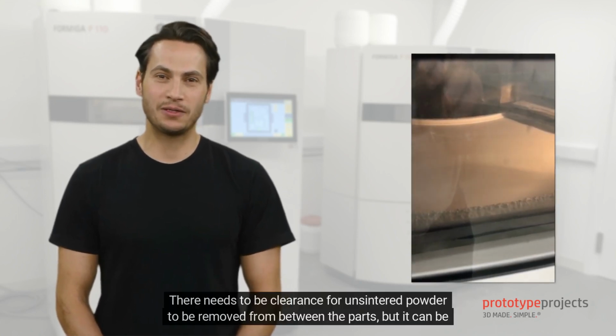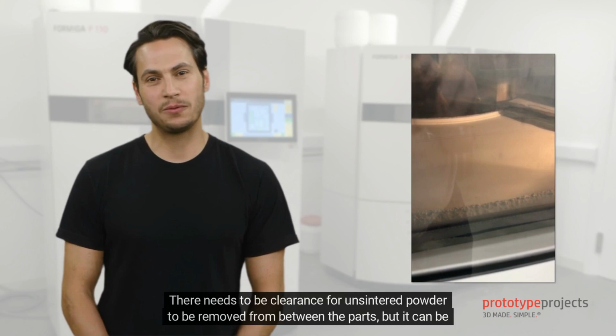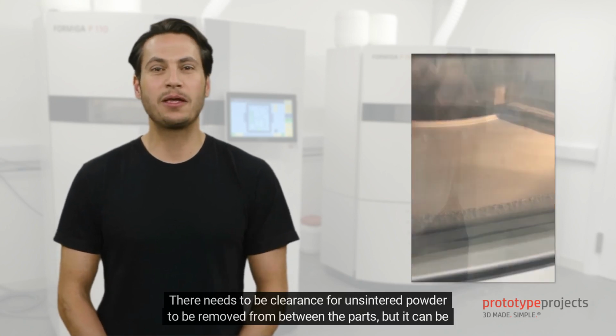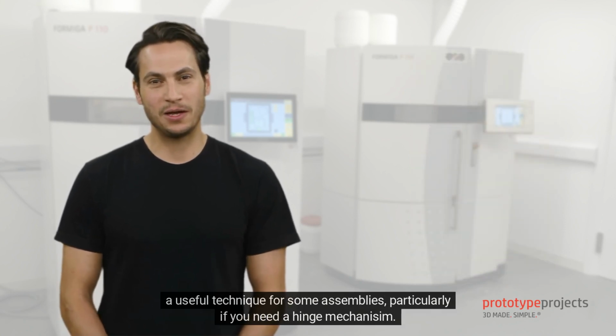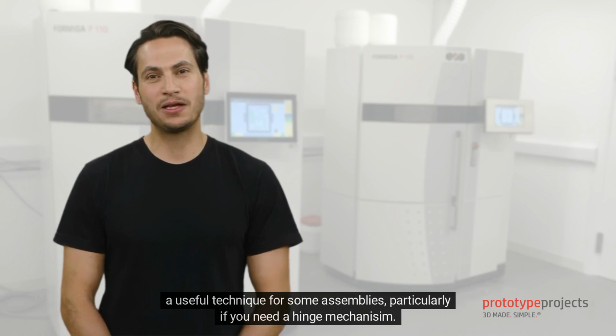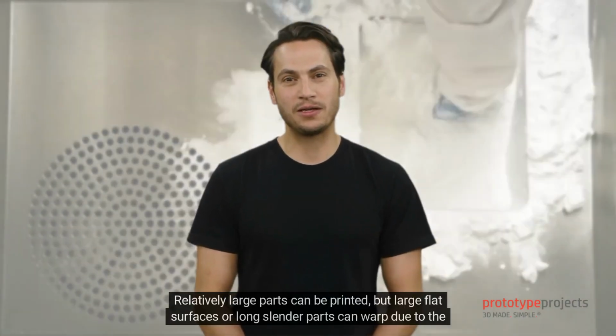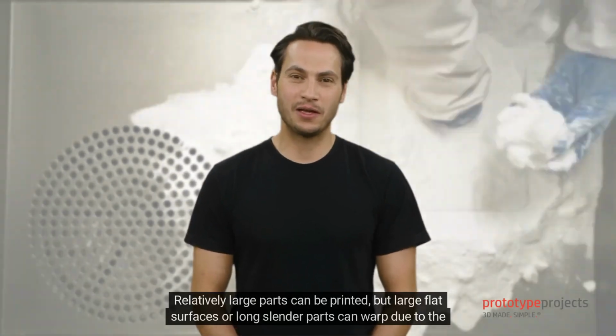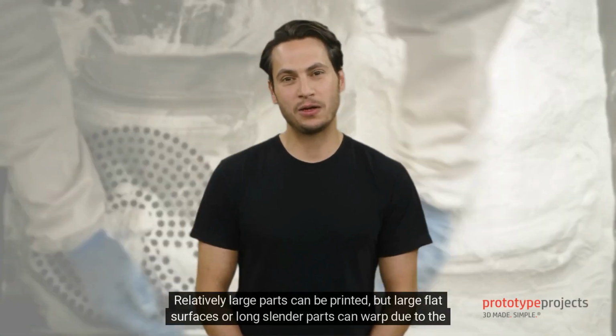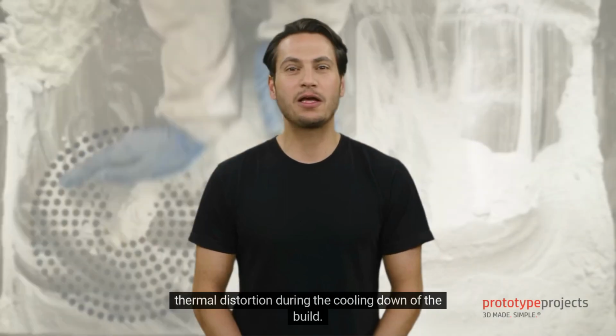There needs to be clearance for unsintered powder to be removed from between the parts, but it can be a useful technique for some assemblies, particularly if you need a hinge mechanism. Relatively large parts can be printed, but large flat surfaces or long slender parts can warp due to the thermal distortion during the cooling down of the build.